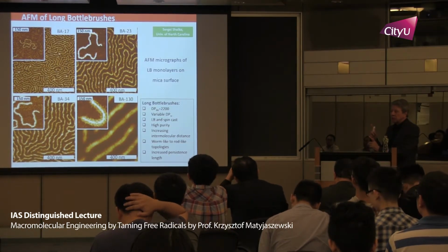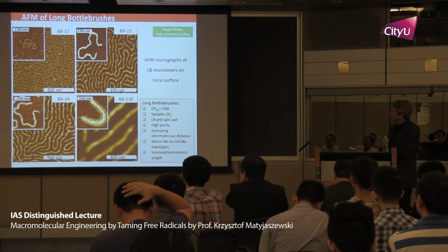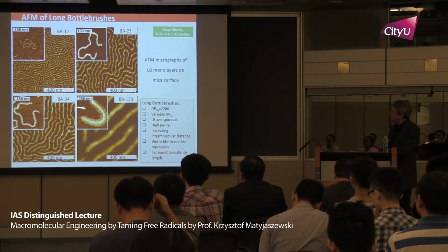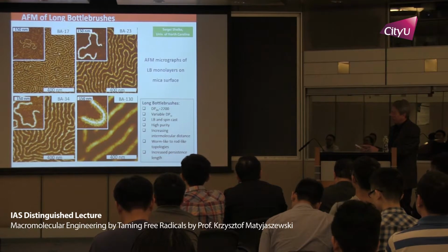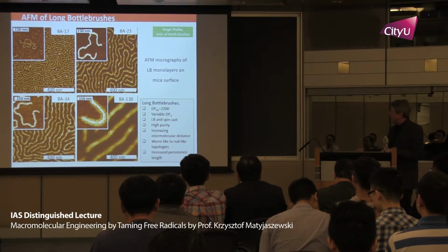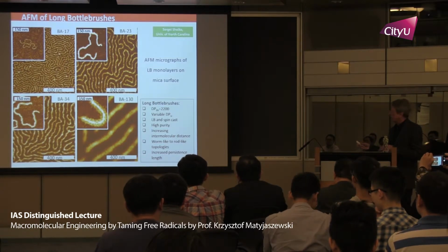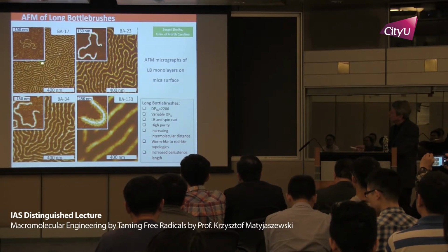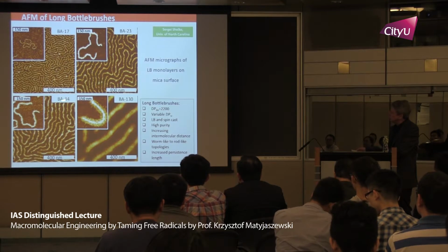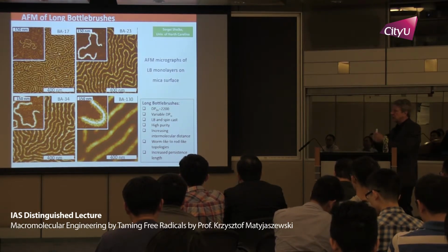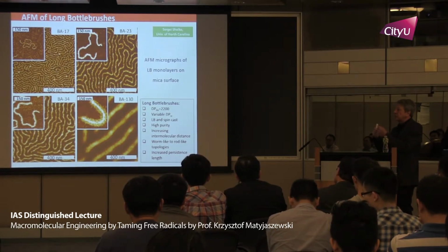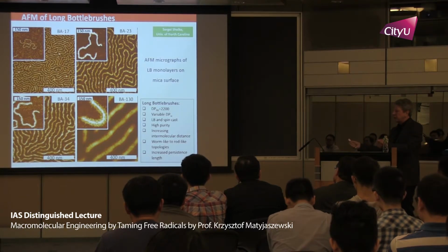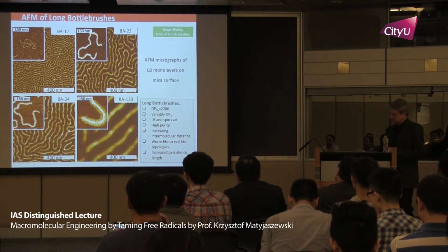You see two phenomena. One is that these brushes become more and more separated, one from another, because a lot of side chains are lying in between. What you see here are dissolved side chains in fact. But the second is that you see them progressively getting more and more stretched, because these side chains become longer, they want to go on a mica surface and stretch the backbone.